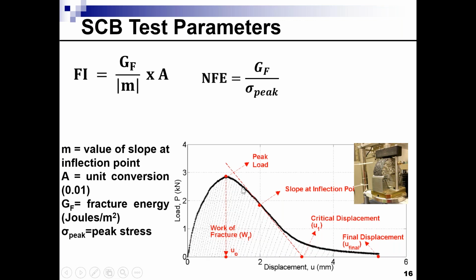And through the load displacement curve that you see here, we analyze the data and get the work of fracture, or the fracture energy, which is the area under the load displacement curve. Then we divide that by the slope of the post-peak curve that you see here, and multiply that by a conversion factor, and this will give us a flexibility index.